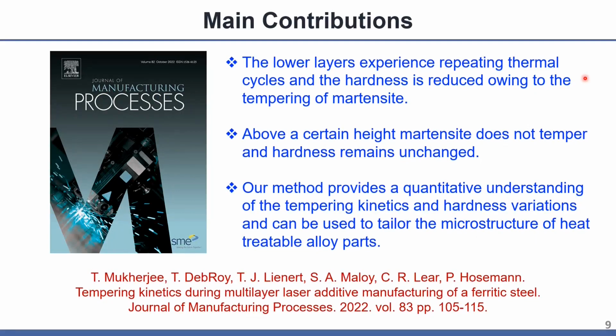We found that the lower layers experience multiple thermal cycles and the hardness is reduced due to tempering of martensite. But above a certain height, martensite forms but does not temper, and as a result, the hardness remains unchanged in the upper layers. This investigation provides a quantitative understanding of the tempering kinetics and the hardness variation. This same approach may be used to tailor the microstructures of other heat-treatable alloy parts. We have published this work in the Journal of Manufacturing Processes, and here is a reference to this paper.